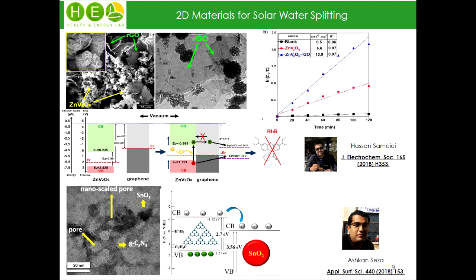In another project, conducted by my former master student where I was co-supervisor, Ashkan developed a method for the first time, which was microwave assisted. During this synthesis method, in a one-pot approach, we produced graphitic carbon nitride and also nanoparticles of tin oxide at the same time on such a structure. Again, we benefited from the charge separation because of such heterojunction for the water splitting reaction.